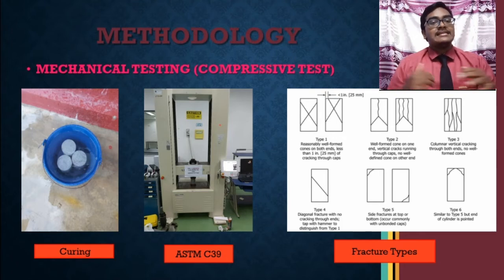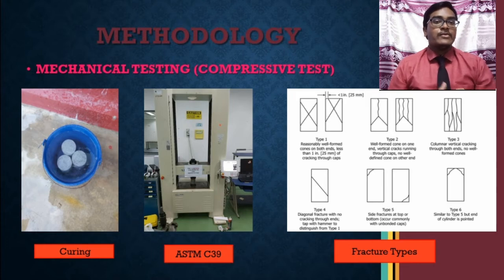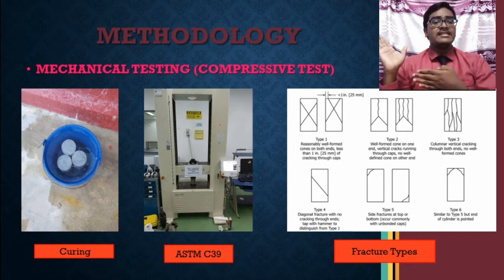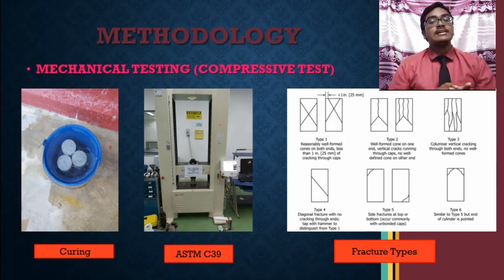Okay, now mechanical testing for concrete composite. There was one mechanical test carried out in this research, which was compressive testing. The experiment undertaken in this analysis adheres to ASTM C39. As you can see in the figure, it shows the compressive testing machine with a maximum of 100 kN. Determine the fracture type and then enter the load and fracture type.